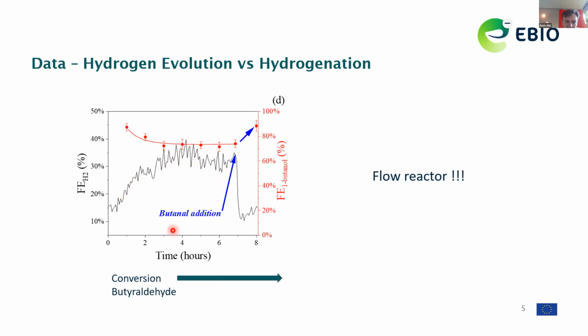If we add some fresh butanal to the batch reactor, you can immediately see that we suppress the hydrogen Faraday efficiency again to below about 20%, and we increase the butanol Faraday efficiency again to levels up to about 90%. So similar to Bastian, but for a completely different reason. And having a batch reactor with changing concentrations over time, a flow reactor could really be a good solution to maintain the feed concentration at the same level, and therefore have a constant Faraday efficiency towards hydrogen, which is low, and a high Faraday efficiency towards the alcohol.